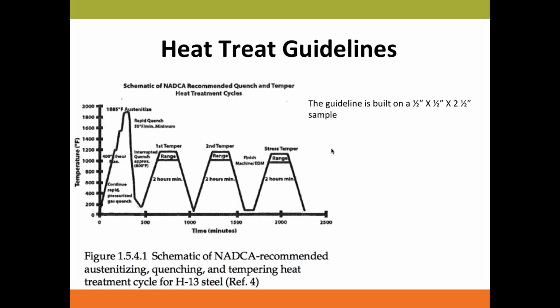So now you've got your steels. When you actually get your steels, they are before heat treated, or there is no heat treat process done to them. It's just coming out from the mill. You can see here from the NADCA guideline the recommended austenitizing, quenching, and tempering for the heat treat cycles. It has 4 different temperature peaks. The purpose of the first one is to try to melt, or not melt, but solutionize all the alloys in the steels. You can see the chromium, molybdenum, or tungsten goes back into the steel, and now you have first temper, second temper, and the last stress temper to release the alloy back out to get the property that you want.